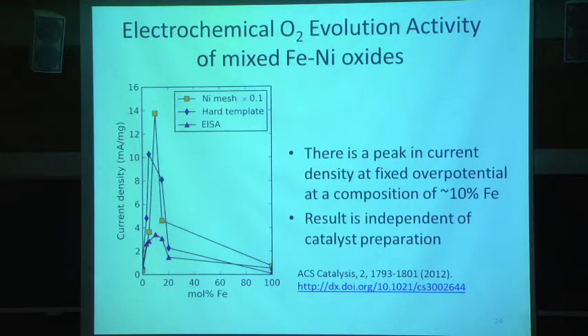And we think that's because you have the metal oxide directly on the current collector that's made out of nickel. So you have extremely good electrical contact between the oxide and the catalyst. But the position of this maximum is about the same for all of them. At least we don't think there are very important differences in here. So the result is essentially independent. Somewhere between 10 and 15% iron, you get a maximum in activity in the electrocatalyst.